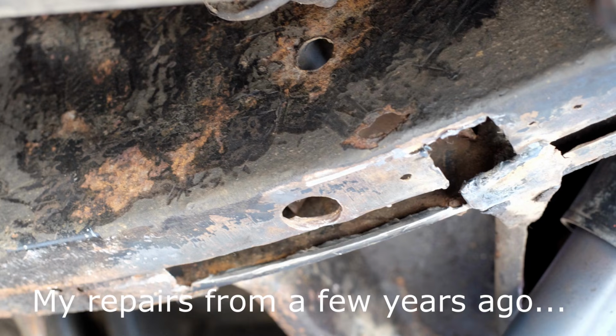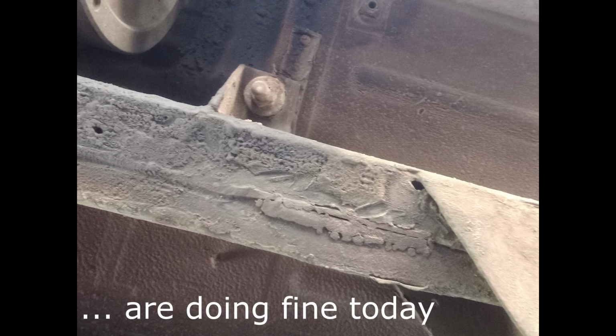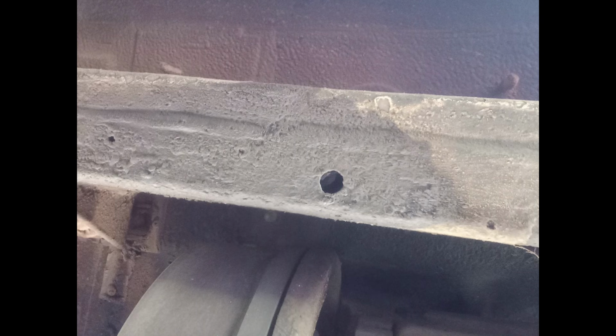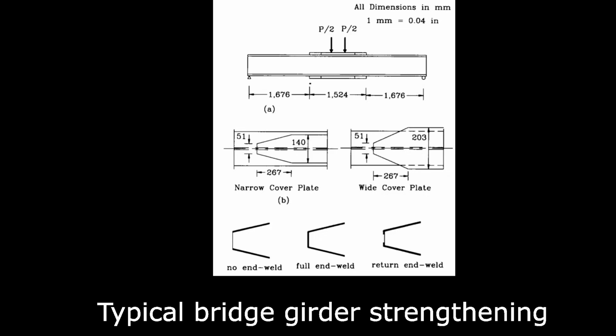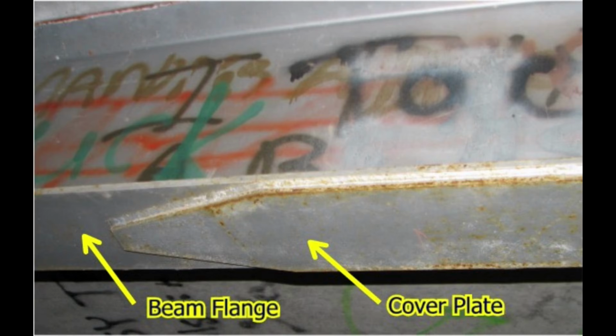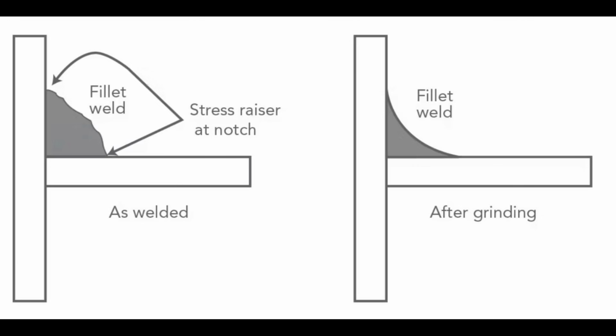However, if there's any doubt about the butt welds, you can put a cover plate over the top to reinforce it. And there's plenty of experience of this with bridge girders, which are likewise fatigue sensitive structures. The cover plate needs to be seal welded all the way around so you can't get water behind, creating a corrosion problem. And at the end it needs to be faired in so you don't get a dramatic transition, and pay particular attention to grinding the toes of the fillet welds, because that's where fatigue crack initiation will occur.